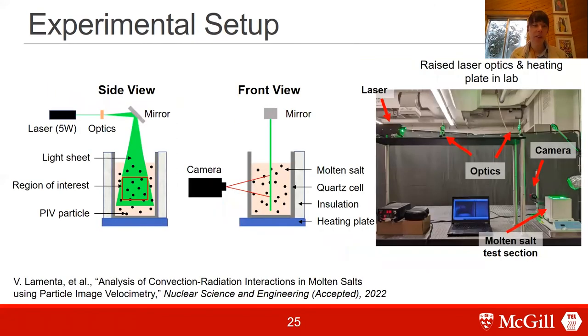And here you can see our experimental setup. The way that it works is we have our molten salt contained in a vessel, and we disperse particles inside the molten salt that are really good at scattering light. We use some optics to produce a laser sheet. The laser gets scattered by the particles, and we use a camera to capture that scattered laser light, visualize the particle motion, and use that to get the velocity distribution. So you can see our laser, optics, camera, and our molten salt in our test section that we're using to study our molten salts.